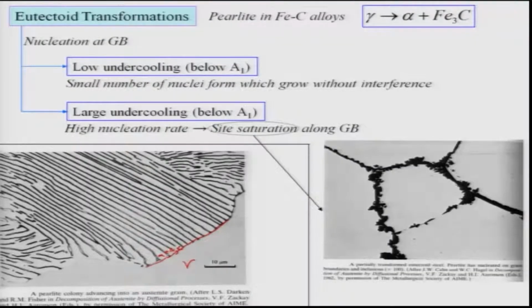But before that, let me tell you, in most cases nucleation of these phases happens along the grain boundaries of the gamma phase. These are the gamma grains. That is obvious, because the grain boundaries, grain corners, grain edges, or even triple points are the regions where the nucleation probability is high. We have seen that in our discussion on nucleation. The same thing will happen here also. So all the nucleation will start from the grain corners, grain boundaries or maybe edges. That is what is seen here.